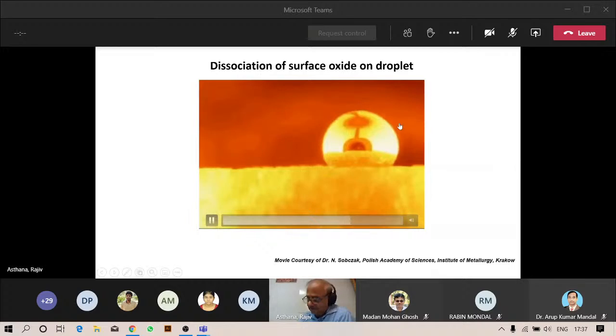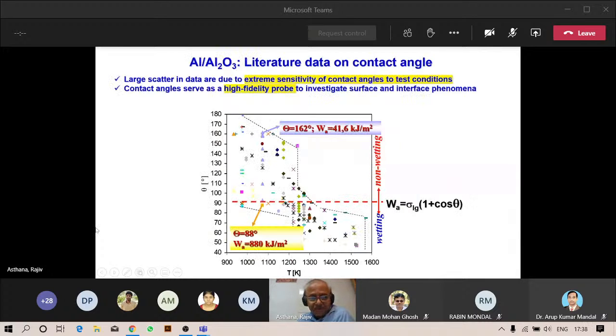So basically, if you look at the data on contact angle of aluminum on the aluminum oxide substrate, you see the results all over the place. So here, contact angle versus temperature in alumina gives you values that can go from less than 90 degrees to over 170 degrees. And that is because the contact angle is extremely sensitive to the substrate condition and also the testing conditions. That is a challenge, but that is also an opportunity because contact angle measurements can serve as high fidelity probe to investigate surface interfaces. So that was the focus of our work, that we wanted to use measurements of contact angle to investigate the bonding in ceramics and metals.